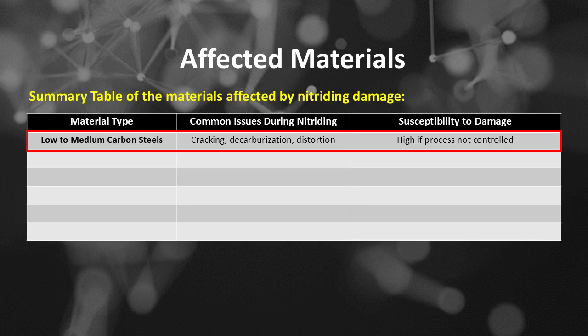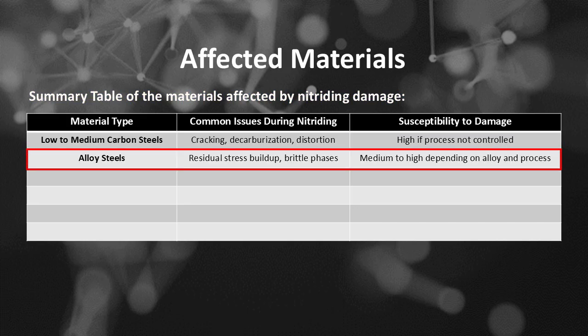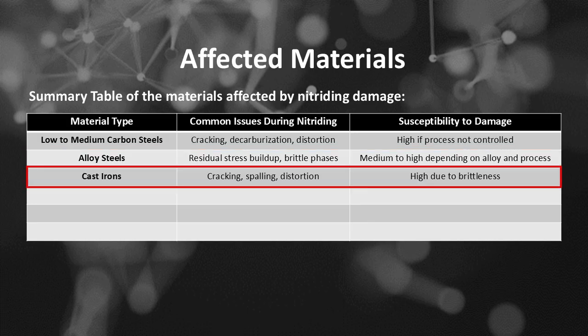If material type is low to medium carbon steels, then the common issues during nitriding will be cracking, decarburization, distortion, and the susceptibility to damage will be high if process not controlled. If material type is alloy steels, then the common issues will be residual stress buildup and brittle phases, and the susceptibility to damage will be medium to high depending on alloy and process. If material type is cast irons, then the common issues will be cracking, spalling, distortion, and the susceptibility to damage will be high due to brittleness.